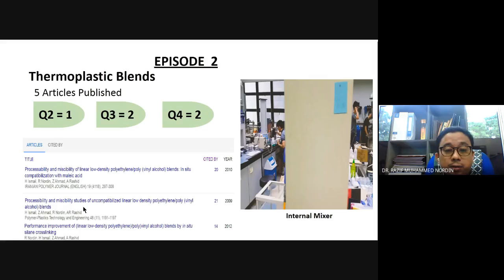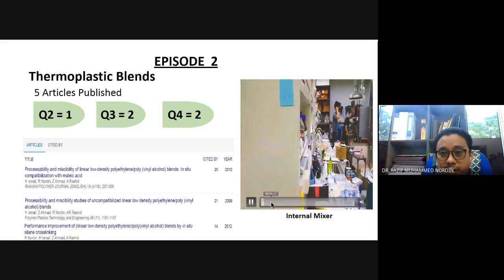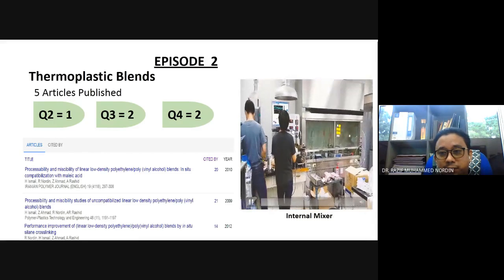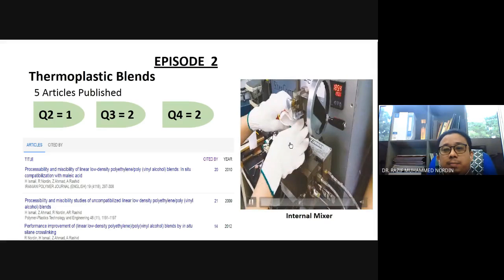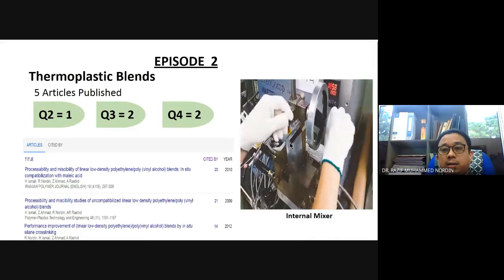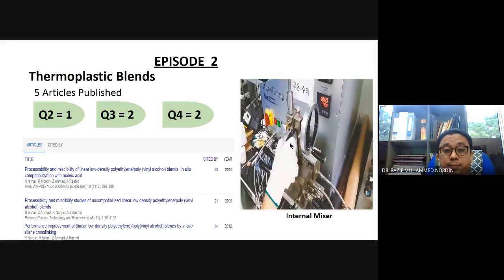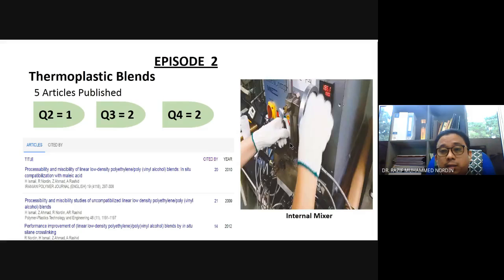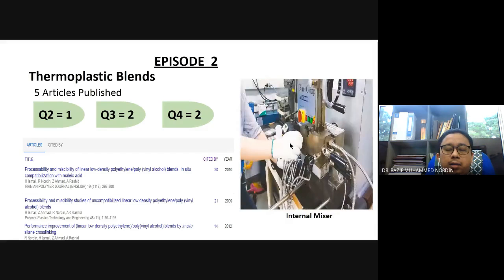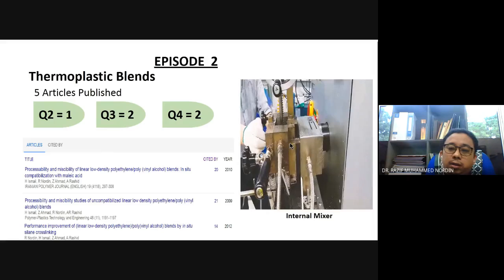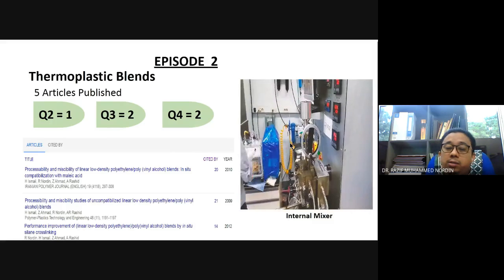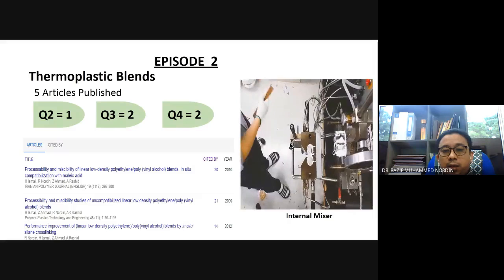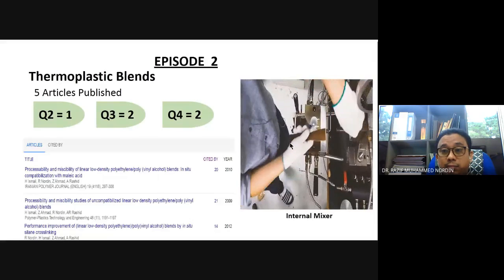Okay. So for this process, during my PhD, I use the internal mixer itself. Okay, let's take a look at the mixer. This is the mixer itself. For processing plastic, you need to take into account the melting point of the material, because for polyethylene, the melting temperature is about 123 degrees Celsius. So you need to increase about 10 to 20 degrees. So I choose 150 degrees. And the process is very fast, about 6 minutes.